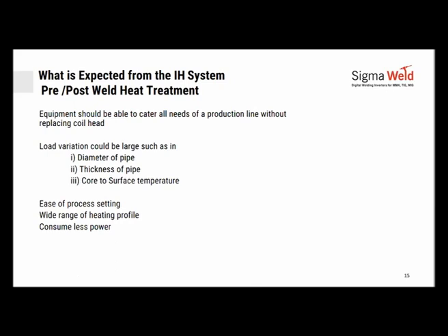What do you expect from an induction heating system for pre-weld, post-weld applications? You expect the equipment to be able to cater to most of your production line needs without replacing the coil head. So as somebody was asking, if you had a pipe or an elbow or a nozzle to flange joint, which was say 18 inches today, and tomorrow that was to be about 24 inches, the ease of doing both without having to change the coil would be required. It should compensate for your load variation, thickness of pipe, diameter, surface to core temperatures, ease of process setting, wide range of heating profile, and it should consume less power.